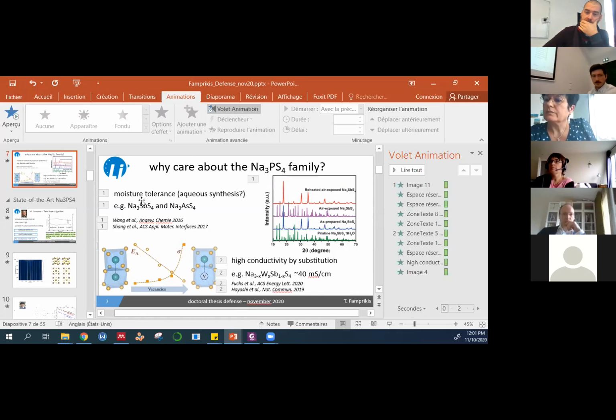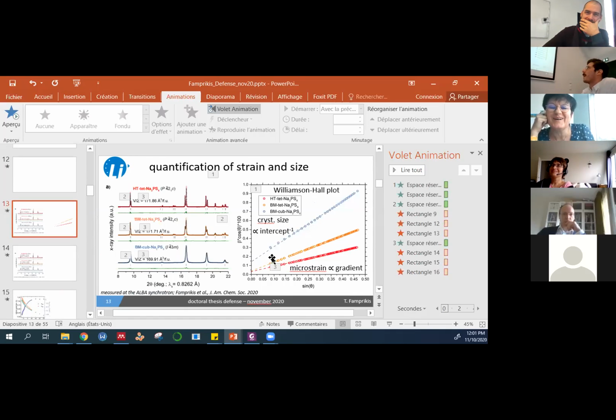Okay. So I had a last question. I had others, but I think I have to leave the floor. Concerning the Williamson-Hall plot, I was surprised, in fact, by this very nice plot. And as mentioned by Gwen, because you mentioned in other pages in the manuscript that you had a microstructure effect, I would have expected, for some specific orientation, because if it is an isotropic material, you can plot this plot, considering whatever crystallographic plane, but for a material with a specific microstructure, and you mentioned it in your manuscript, but for me it was not clear from the figures you gave in your manuscript.